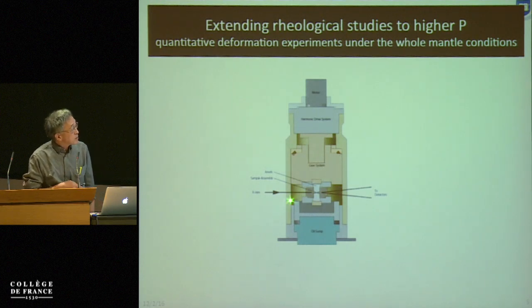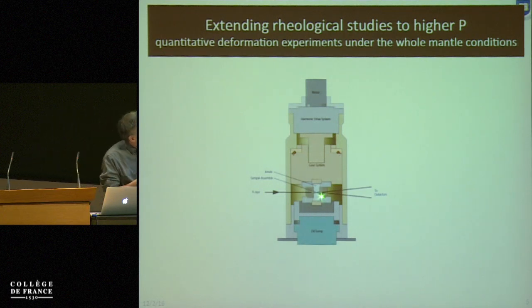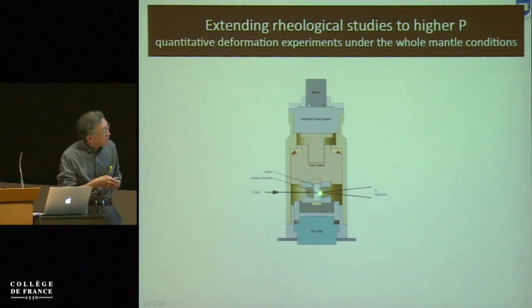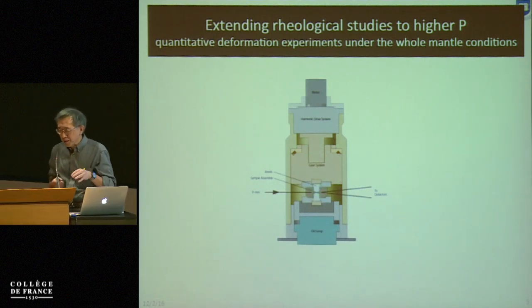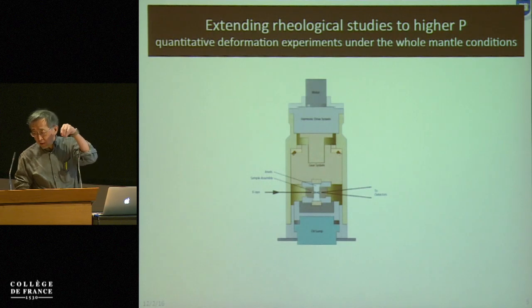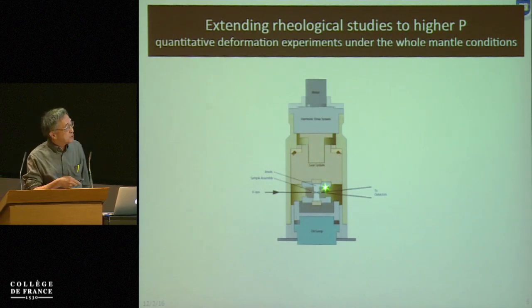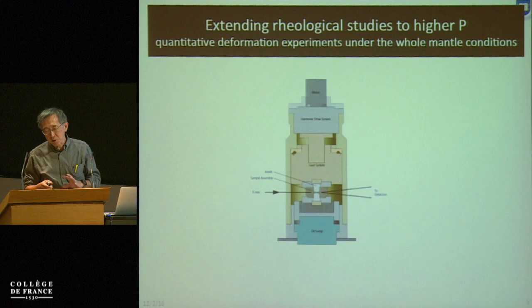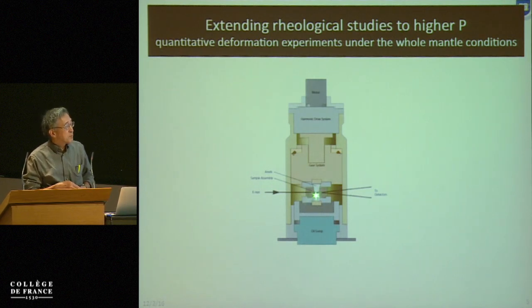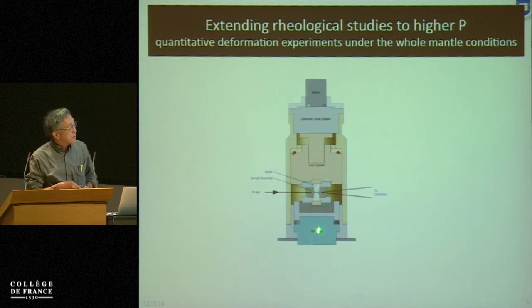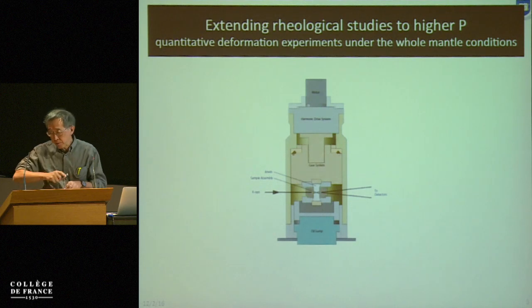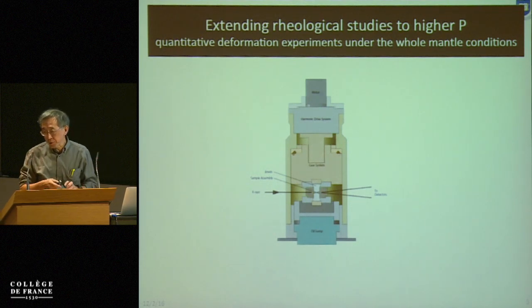So this is the apparatus which I designed. Essentially, this is an apparatus in which you squeeze your specimen with two anvils, like a diamond anvil. It's not diamond, but an anvil. Uniaxial compression, and then you have to put lots of stuff here. There are a heater, your sample, insulation material, etc. Then you generate high pressure and temperature here, and then you rotate one part relative to another by motor, and slowly you do the torsion shearing test.